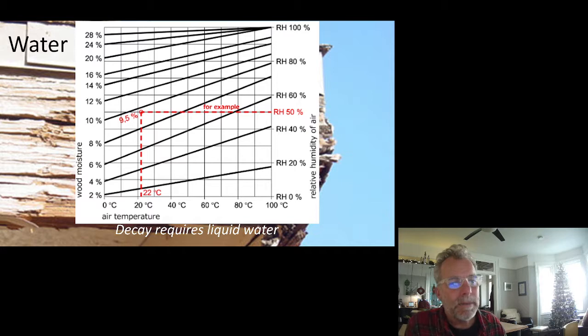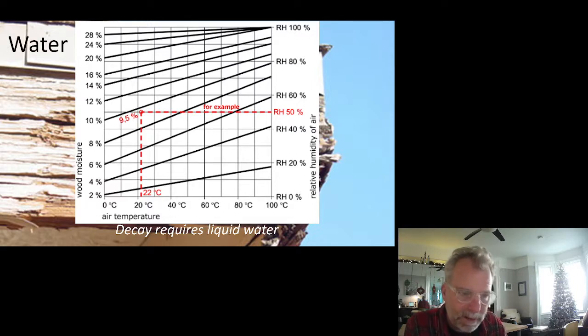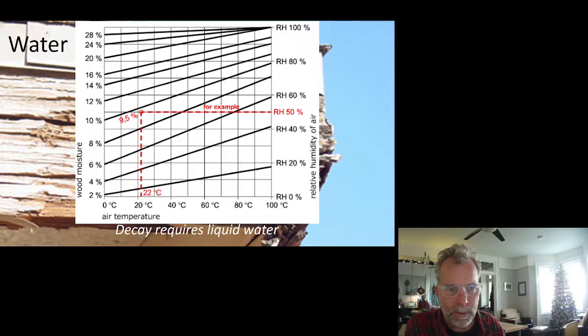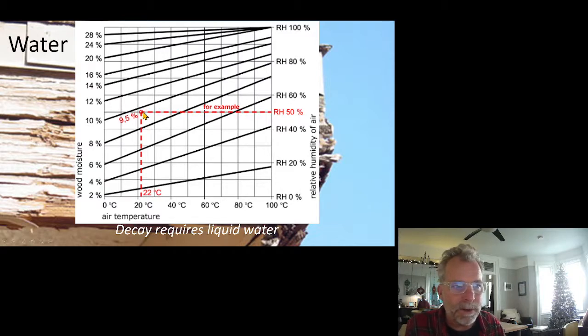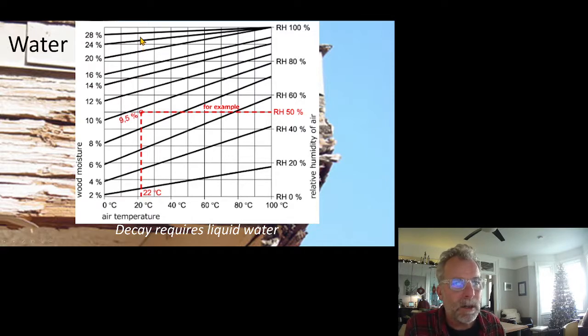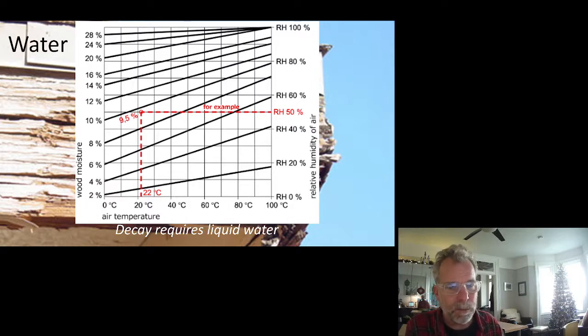There is a graph showing that liquid water results in a moisture content of wood in excess of about 25%. A moisture content of 25% is about when decay will start. Moisture content is not the same as relative humidity. At a relative humidity of 50% and a temperature of 22 degrees — a normal interior building condition — the moisture content in the wood is under 10%.